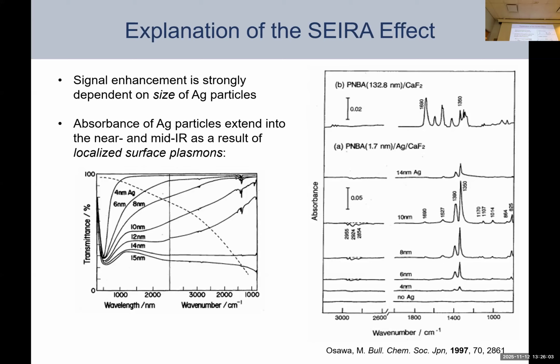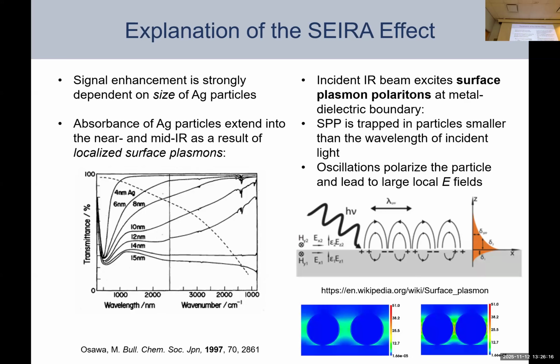Essentially, what we're going to do is take advantage of this large absorbance feature on the silver nanoparticles or other metal nanoparticles. Okay, and we're going to get localized surface plasmons that can become in resonance with the incident IR beam. And so this now generates surface plasmon polaritons at our dielectric boundary between the particle surface and the electrolyte. Okay, so these oscillations are going to polarize the particle, and they're going to lead to really large local electric fields. That's sort of what's being depicted here, okay?